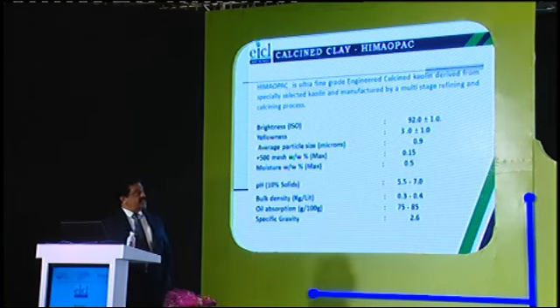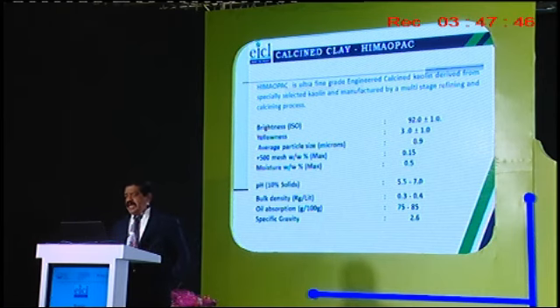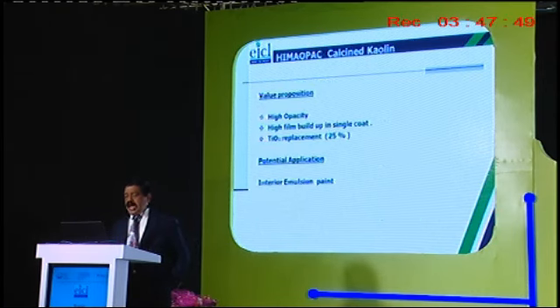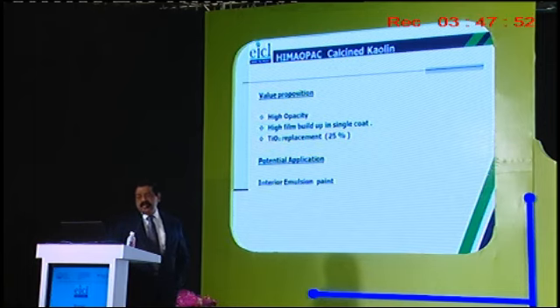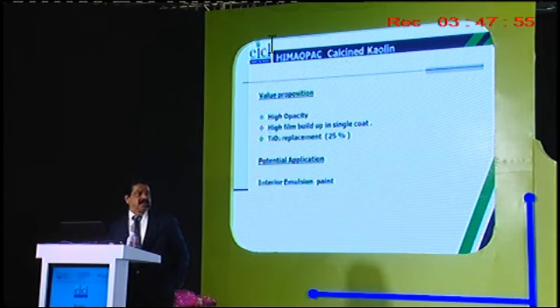Now this is an engineered calcined clay we have introduced with very high opacity. You can see high opacity and high film build in a single coat. There is a change in the tendencies of the coating industry from multi-coat to single coat, where you apply one coat and get the hiding. For these types of paint we can use this product, Himaopac, and the potential application is interior emulsion paints.